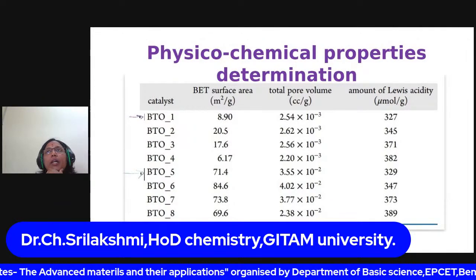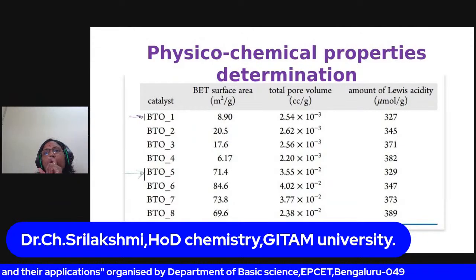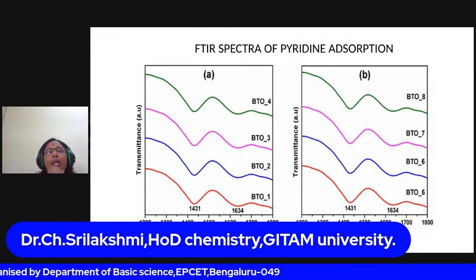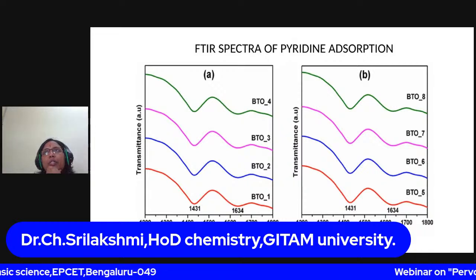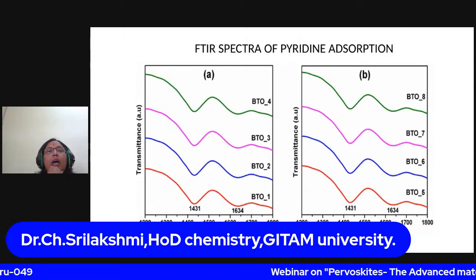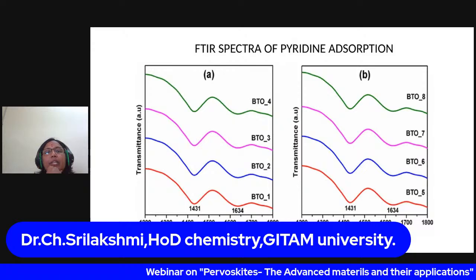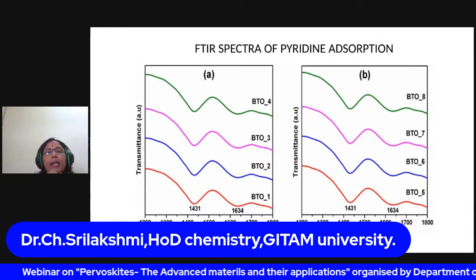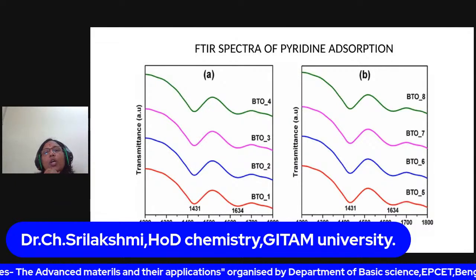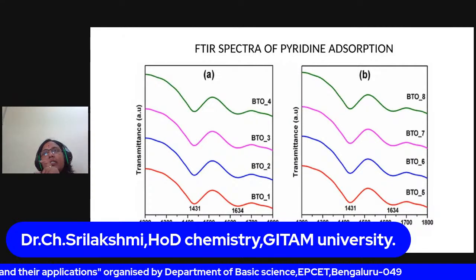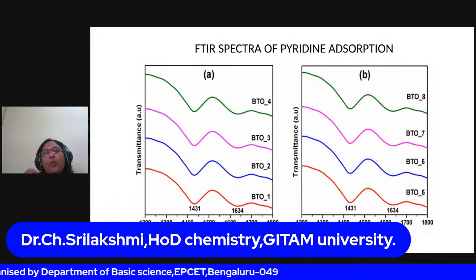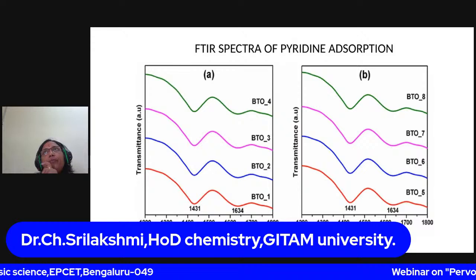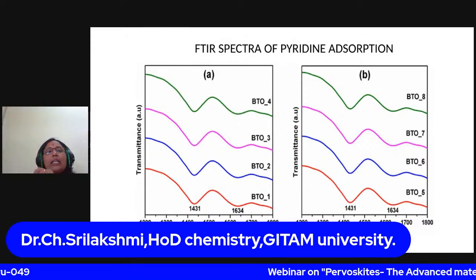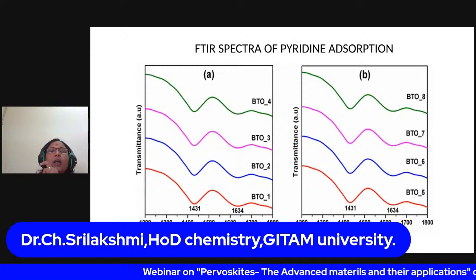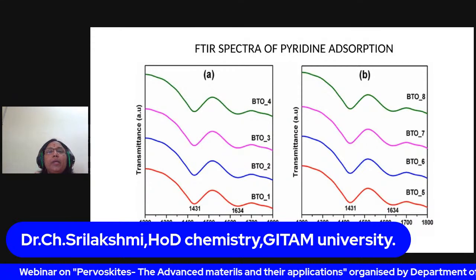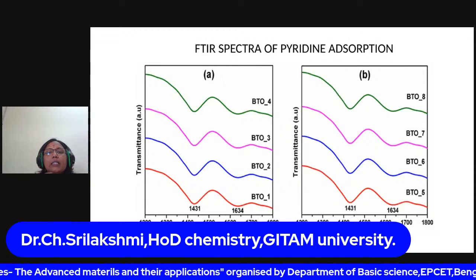So how do I confirm that the acid sites are Lewis acid sites but not Bronsted acid sites? We have done the pyridine adsorption studies using IR spectroscopy. In the IR spectra of the pyridine adsorbed samples, we observed two bands at 1431 and 1634, which belong to pyridine chemisorption on Lewis acid sites. If it were Bronsted acid sites, it should give a peak at around 1550, which is absent here. So it tells that only Lewis sites are present in the barium titanate and chromium doped barium titanate samples, and Bronsted acid sites are absent.